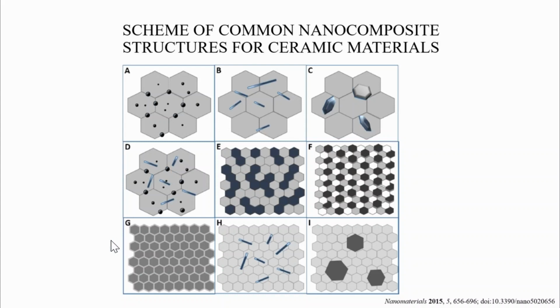Nanocomposite structures in ceramics often involve a micronic size matrix. Here you can observe it with embedded nanoparticles. These nanodispersions can be situated within the matrix grain and grain boundaries or occupy both positions, as illustrated on figure A. A classic example is found in the pioneering work of Niihara and colleagues, who dispersed nano silicon carbide particles within micronic aluminum oxide, silicon nitride, or yttrium oxide matrices.